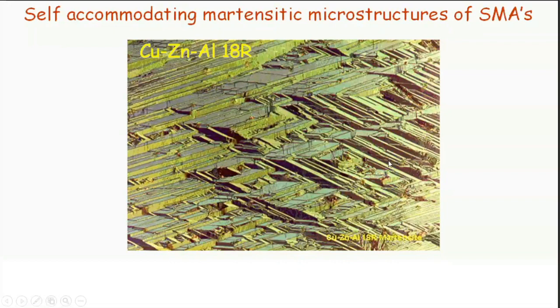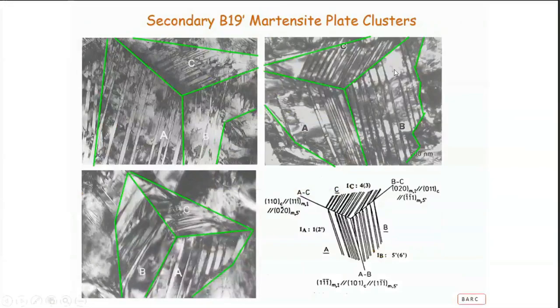So if I take the next slide, what we see is a nickel titanium shape memory alloy, and the examples in this talk will all be from this alloy. And what's different here is that, to start with, you can see these three plates coming together. Okay, I forgot something I should have told earlier on, that this is a transmission electron micrograph, and the contrast you see here is what is called diffraction contrast. It is essentially because the crystals are oriented differently with respect to each other.